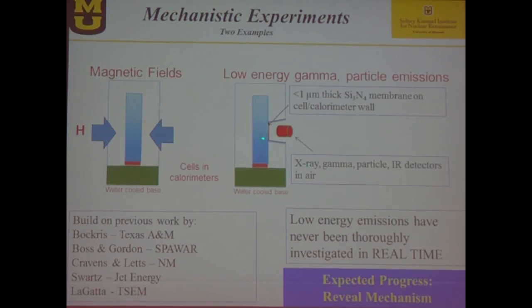So what do we have? We have a silicon nitride membrane which is less than one micron thick. On the other side we have an electrochemical cell, as we know, anode, and the membrane is the cathode. We are plating the cathode, the silicon nitride, with platinum, and the anode is made of palladium. So we have a co-deposition. We thought about that due to all these people who were working in this direction: Bockris, Boss, and Gordon, and Cravens, and Letts, and Swartz, and Lagatta in Padua, Italy.